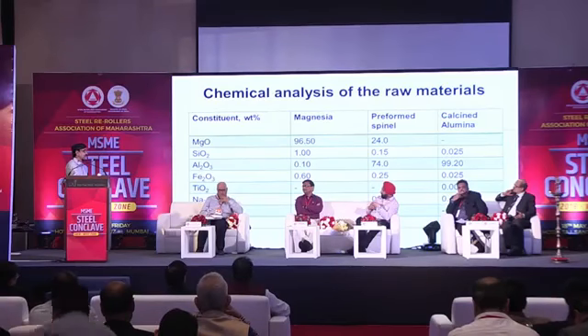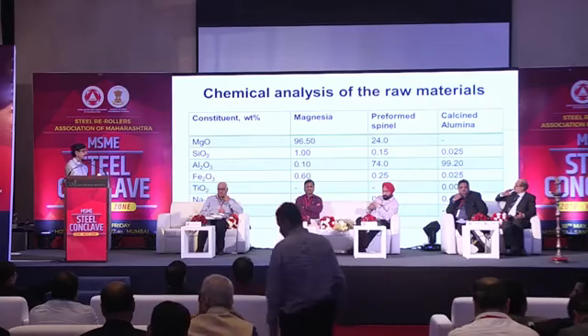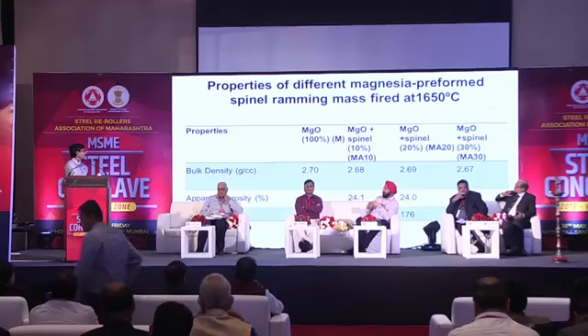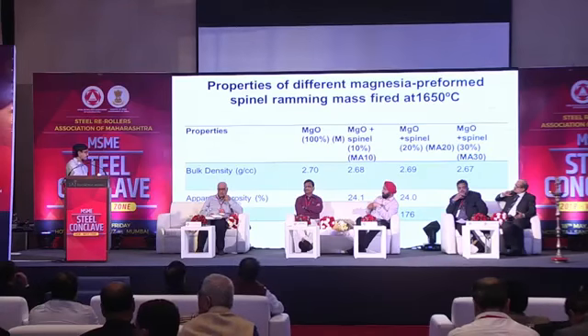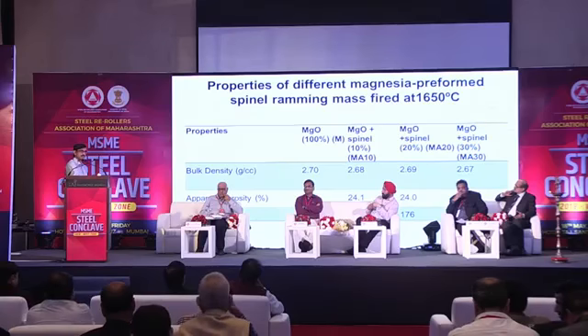These are the typical chemical compositions. So 96 to 97% purity magnesia, that is what is commercially available. When you use some spinel, you can see there is an improvement in the strength. There is an improvement in the thermal shock resistance also, but there is a slight decrease in the bulk density when you use some spinel. That's why, to overcome this, we use some binder to improve the mechanical properties.